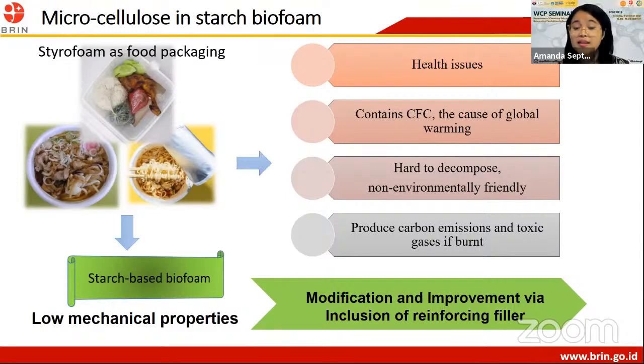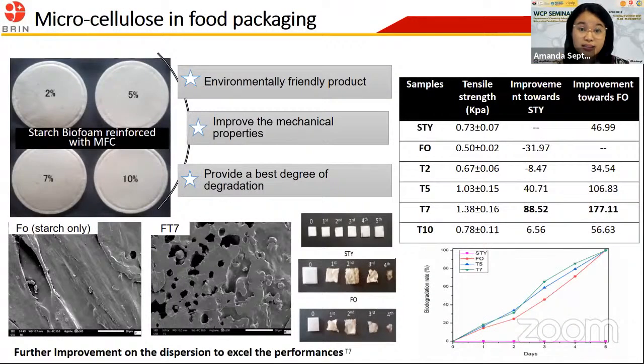So we were thinking that maybe modifying and improving the mechanical properties can be done via a reinforcing filler, our MFC. So here are the results. We can see that our starch-based biofoam with the MFC shows excellent mechanical properties, up to 88% higher compared to the styrofoam itself. And compared to the neat starch biofoam without any filler, our microcellulose can enhance the mechanical properties by up to 177%, which is really a great improvement.